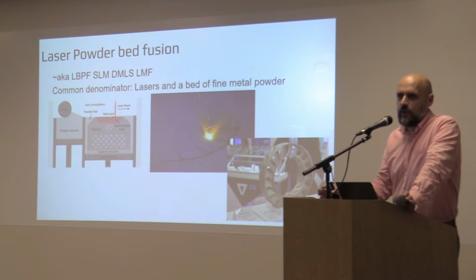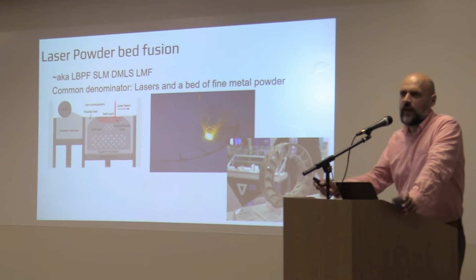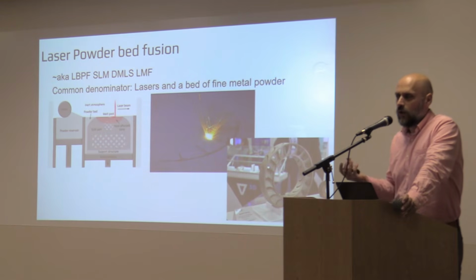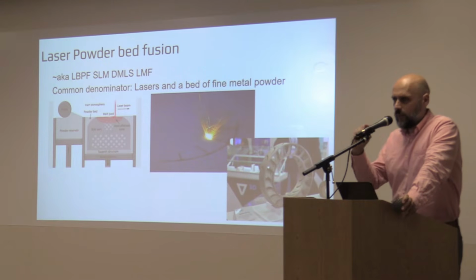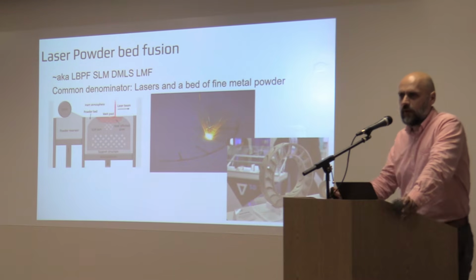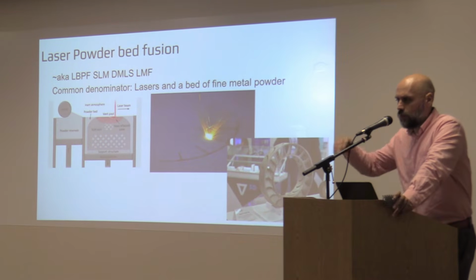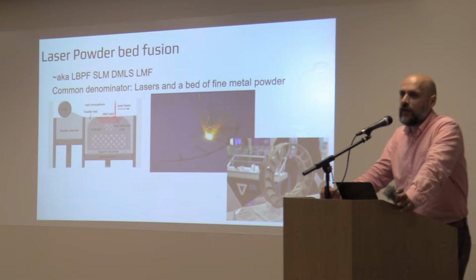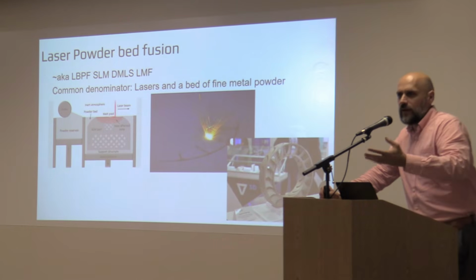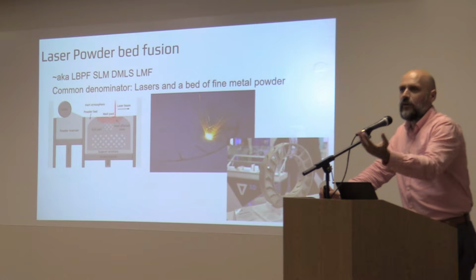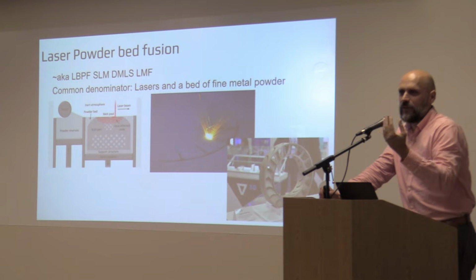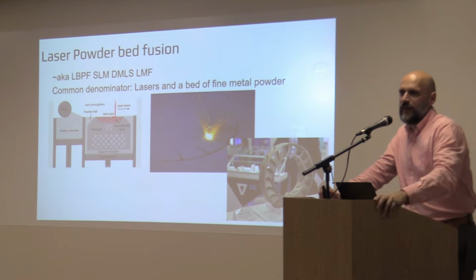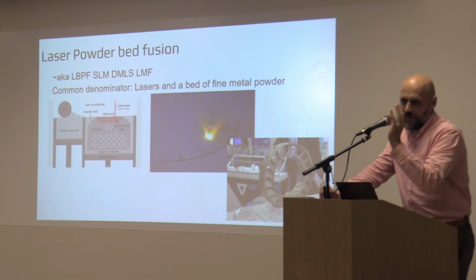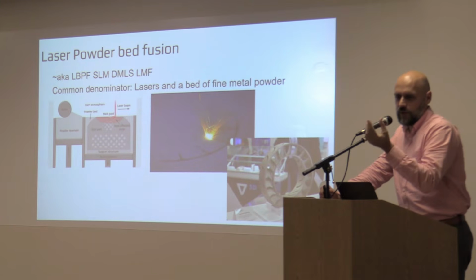It's challenging. The higher you go, you can go faster, but there's other effects that can happen. Like you have a big melt pool, all of a sudden surface tension may take over and wants to ball up, and you don't want that. You want to melt very small pieces, never have it bead, and have a nice control. Because the moment it starts balling, you lose all your edge efficiency. And other things happen. Like the bigger you are, you start sintering the powder around the ball, right? So now it's ugly. It's not smooth. So you have to optimize that.